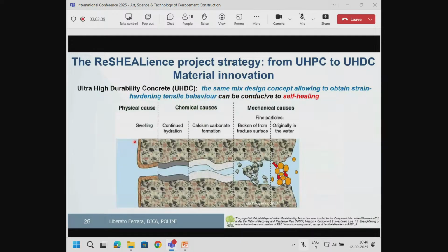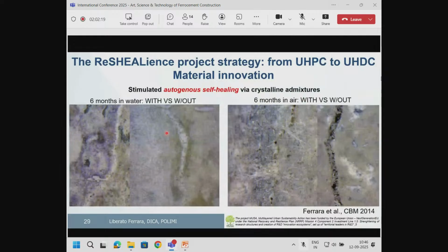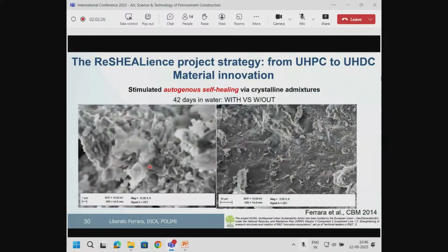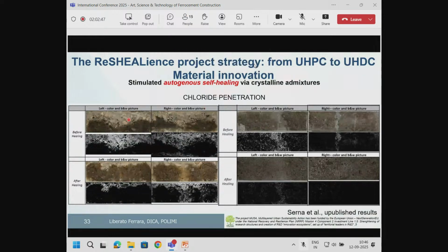We also valued the possibility that this material can self-fill the cracks because of continued hydration and calcium carbonate formation. You can see here some images of cracks which really close up in different exposure conditions. You can see here the growth of the self-healing products where the self-healing occurs, and here where there is no self-healing, images on the microscope, which are quite interesting, and other images of the results that we obtained in our research. Also, for example, delaying, these are classical images for chloride penetration. You see before healing, the area penetrated by the chloride was pretty large, whereas it was fairly much reduced because of the crack seal.